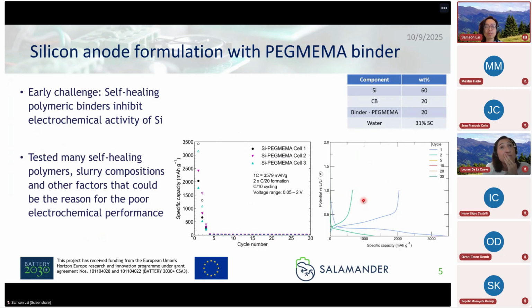We had really bad electrochemistry. The first couple cycles really died. And then we had to spend a lot of time figuring out what was going on here. So we applied a battery of different tests. We thought, maybe it's our silicon. Let's try a different silicon. So we used a commercial silicon, and we observed the same kind of degradation really fast, within 3, 4, 5 cycles. So this is really confusing to us.